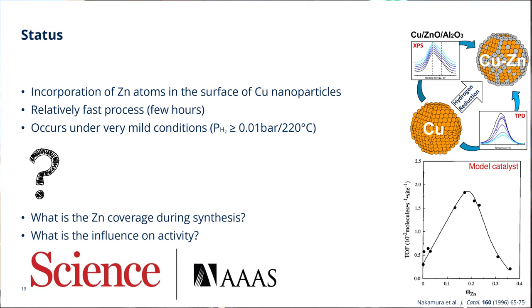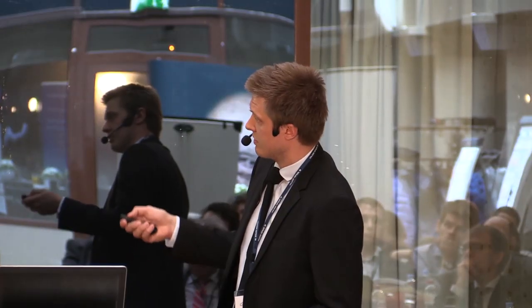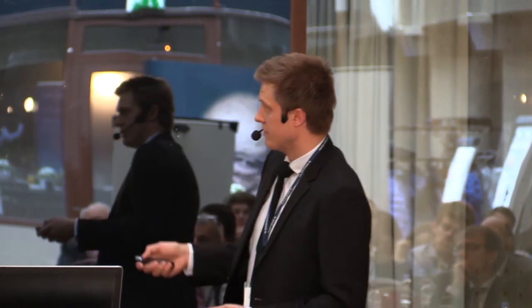For instance, what is the zinc coverage during methanol synthesis? And maybe even more importantly, has this, if any, influence on the methanol activity? The latter part has actually been addressed before, a little more than 20 years ago, by Nakamura and co-workers, where they saw the turnover frequency of methanol against the zinc coverage on your copper particles, where you see a quite steep increase in your methanol activity at zinc coverage lower than 0.2 monolayers.